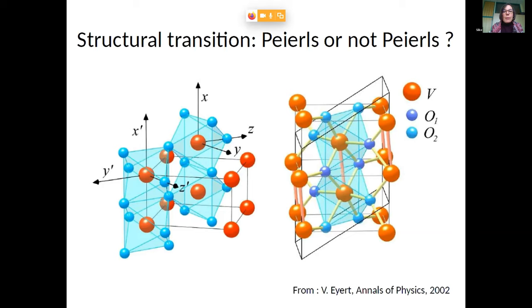Well, the underlying question in this debate is the following. I have told you that the metal insulator transition is accompanied by a structural transition from this high temperature rutile phase to a low temperature monoclinic phase. And as you can see here on this plot, this is actually going along because you double the unit cell in the c direction here. So you have now twice the length here, roughly. And you do that because vanadium atoms along the c axis here pair up. They move a bit closer together pairwise and tilt slightly out of the c axis. And that means that you actually have a dimerized chain-like structure along the c axis.